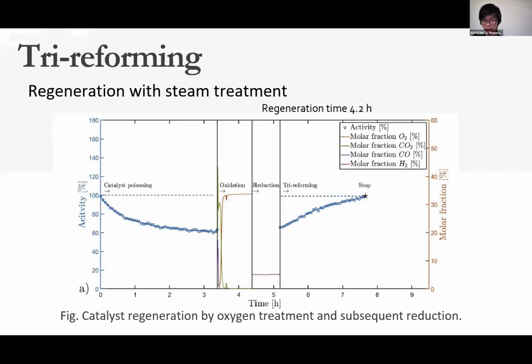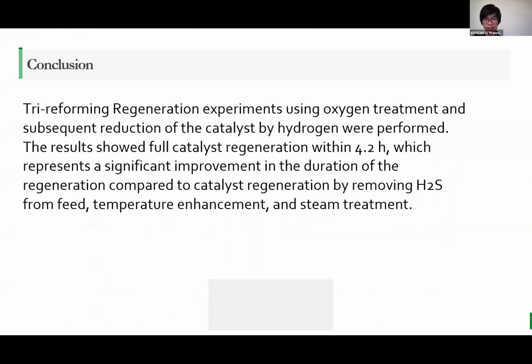Finally, tri-reforming was performed again to investigate the activity of the regenerated catalyst, and an increase of the catalyst activity was observed with time until the catalyst regained full activity after 4.2 hours of tri-reforming.